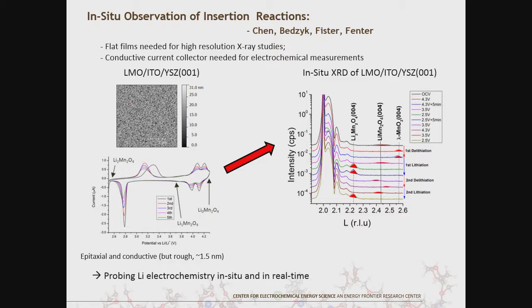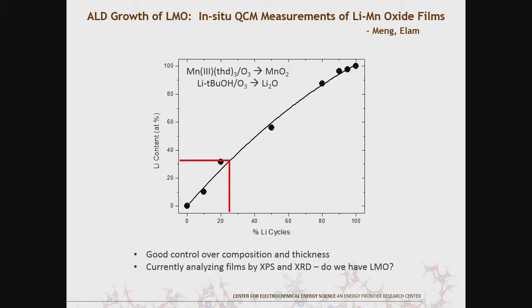What we'd like to do, if we could get high resolution data, we could actually watch the lithium go in and that process of how the lattice gets destabilized. So you can see that down here we're losing capacity. So that's one of the things that's ongoing.